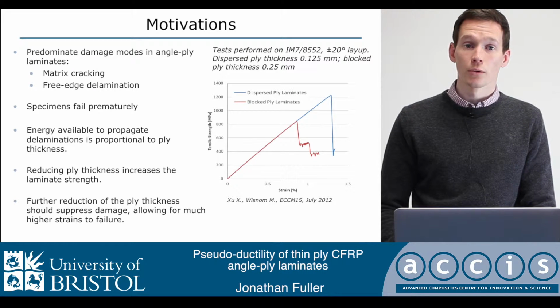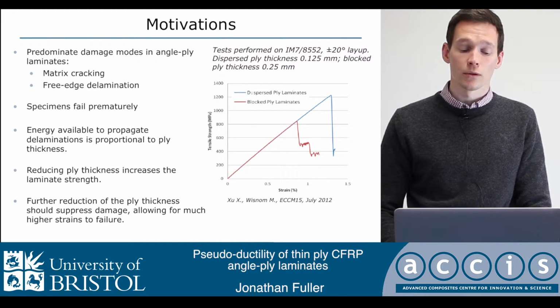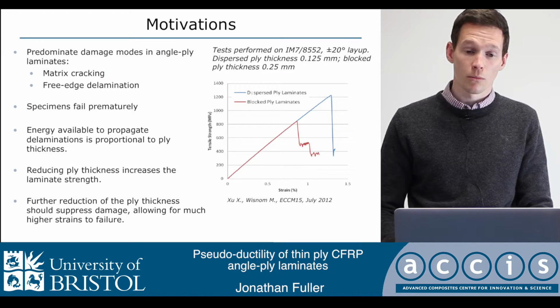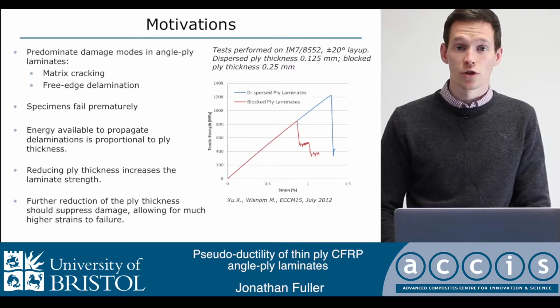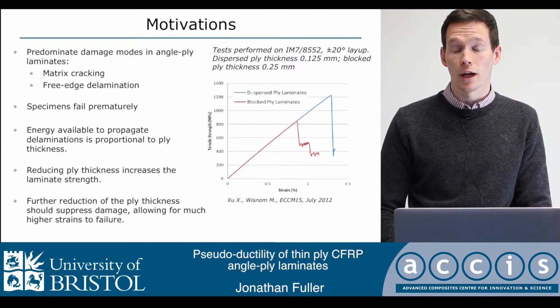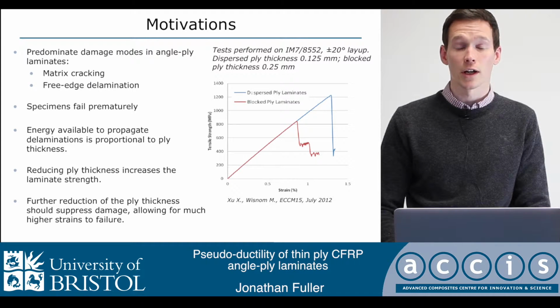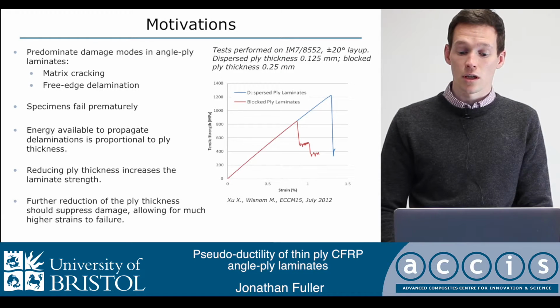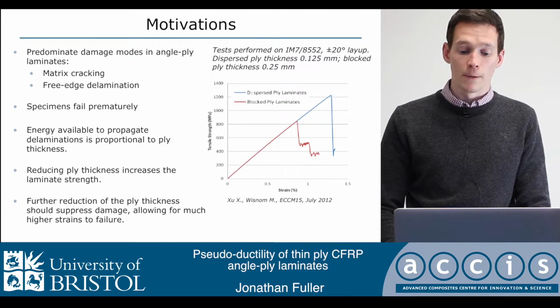So why do this work? Well, many parts of the literature have shown that predominantly angle-plies fail due to matrix cracking and then free-edge delamination, which, as the graph shows, leads to a premature failure, which is the line in red.